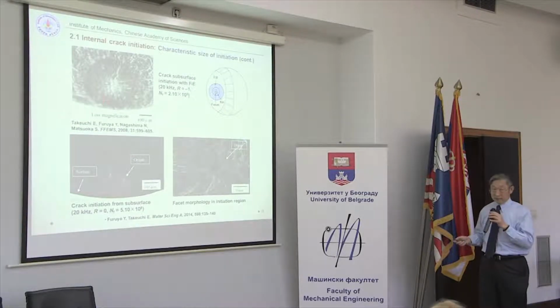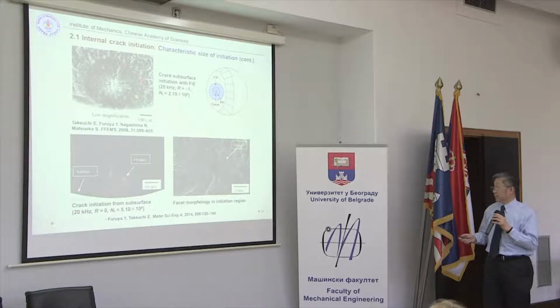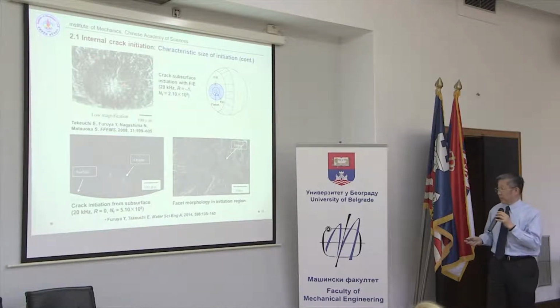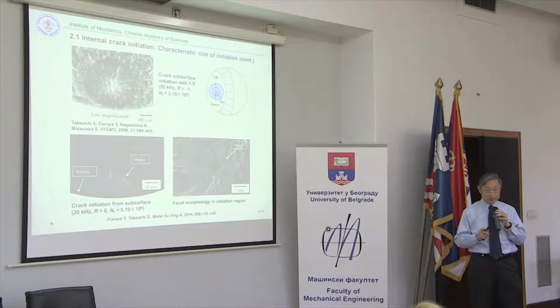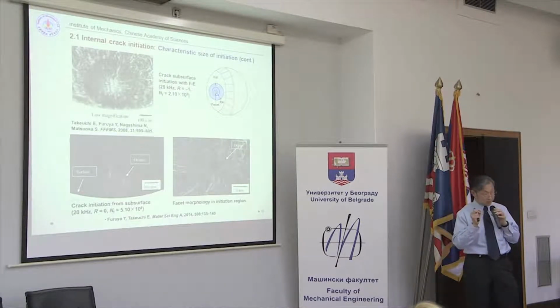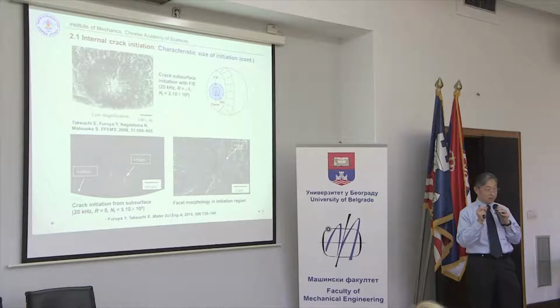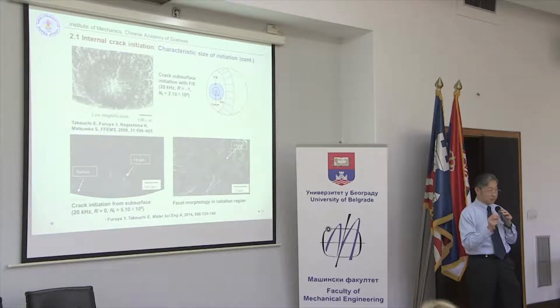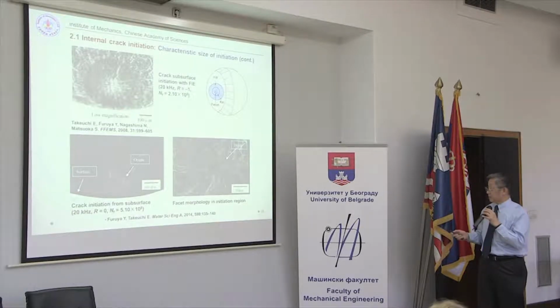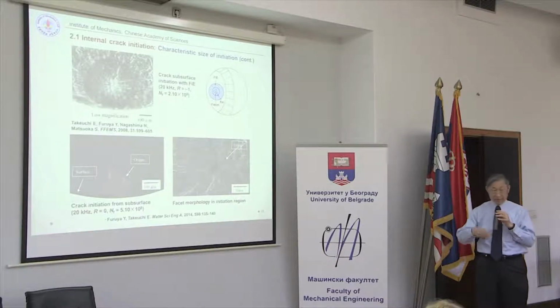And then here are examples for titanium alloys. You may also see the initiation region of fisheye, and also in the initiation site a kind of rough area. But the difference is for titanium alloys, the initiation size is due to the coalescence of cleavage facets, always from the alpha phase of the titanium alloy. So it's a schematic for this coalescence of facets and rough area, and then fisheye and crack steady growth or stable growth, and finally failure.